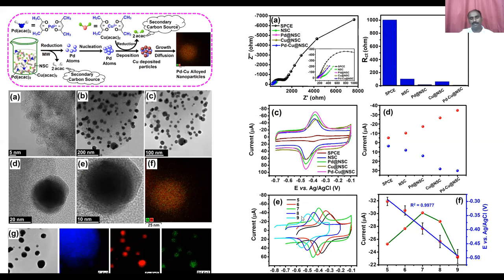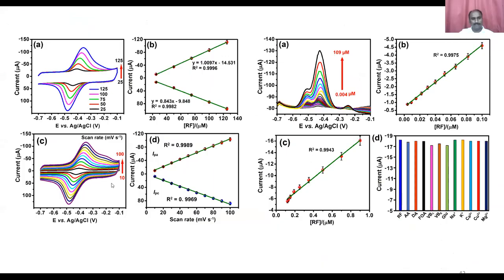is the pH analysis. pH is very important for sensing biomolecules. From a lower pH, from 5 to 9, as the pH level increases, the peak will shift, which means some electrocatalytic reactions happen in this composite. And this is a further CV profile and DPV studies, and some other interferences like ascorbic acid, dopamine, vitamin B1, B2, and glucose, sodium, potassium. Some interferences are mixed together, and these interferences are not interfering in this composite.